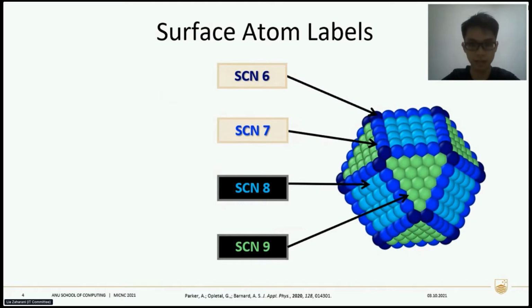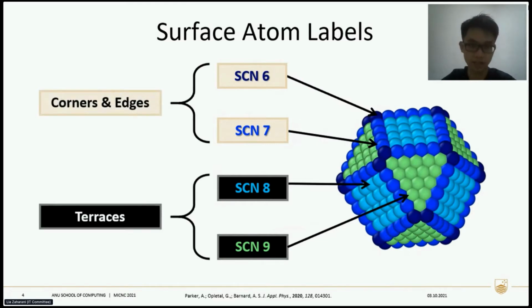Based on this labeling method, the surface atoms are grouped into categories with different ranges of coordination numbers, or simply the number of nearest neighbors of each atom. This is based on the observation that kinks, steps, corners, and edges always have the range of coordination numbers of 4 to 7, while the coordination number of terrace atoms roughly ranges from 8 to 11.